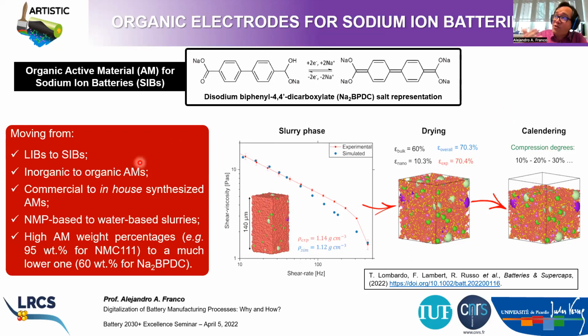Here we move from lithium-ion batteries to sodium-ion batteries, from inorganic to organic active materials. So we move from commercial NMC, for example, to an in-house synthesized active material, which is this Na2BPDC here. And we move from NMP-based slurries, which we simulate with NMC 111, for example, to water-based slurries. And also we move from a high active material weight percentage, typically 95 weight percent of NMC 111 in our simulated slurries, to a much lower one, typically 60 weight percent for Na2BPDC.